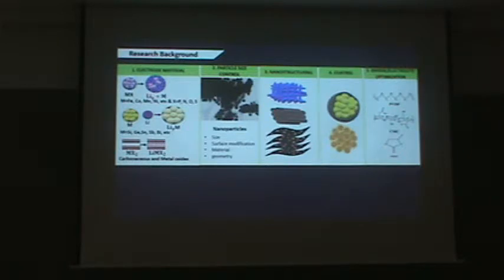Downsizing to a nano scale is very important because it can aid lithium-ion diffusion, but there is an issue with the surface energy, which is high. Thus, the nanoparticles tend to agglomerate. So in many cases, the nano sizing is accompanied by nanostructuring.